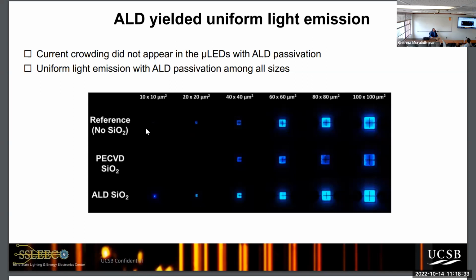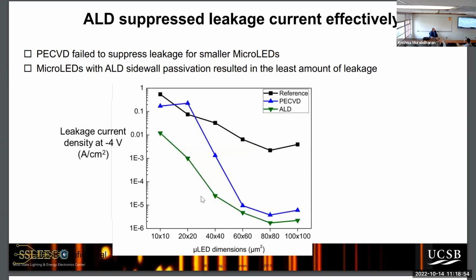So it doesn't work for 10 microns or 20 microns. This is plasma enhanced CVD. This is the normal way silicon fabs put down CVD. And then this is the improved way to deposit silicon oxide. This is atomic layer deposition. And you can see it's not only brighter, but even the small ones light up. And so we only did this 6 years ago. So this helped solve it.